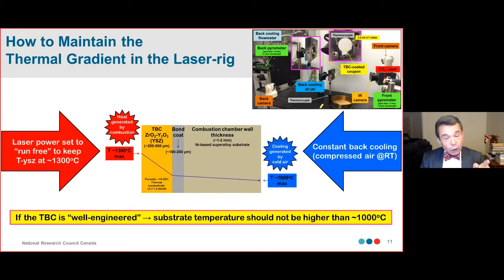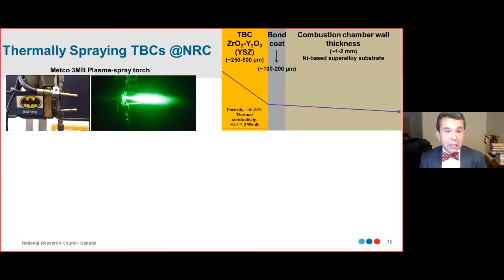So in order to test the TBC, we also have to make the TBC. This is, for example, our standard or benchmark TBC that we created at NRC. We use a plasma spray torch to make the TBC. And as you know, I have been telling you that the minimum thickness is about 250 microns, and the maximum is about 500 microns.